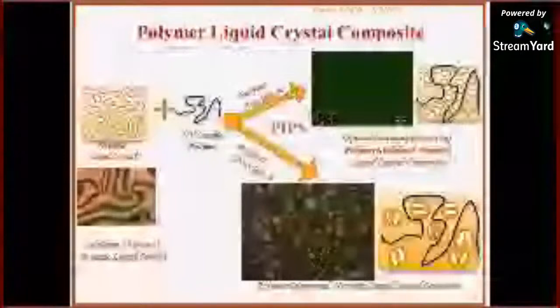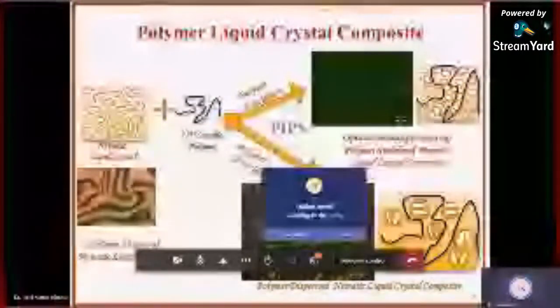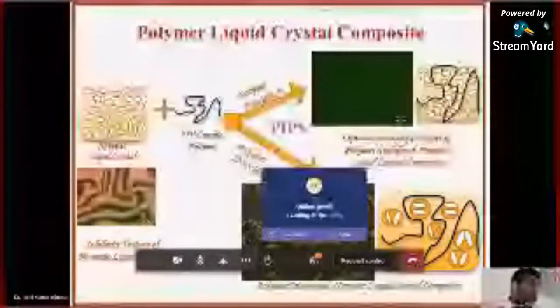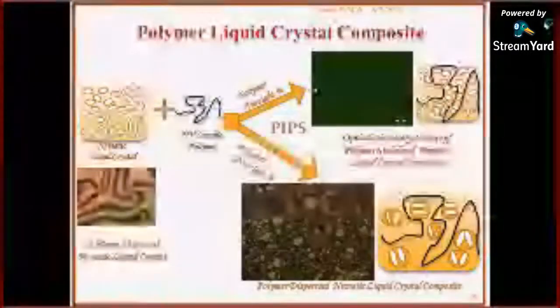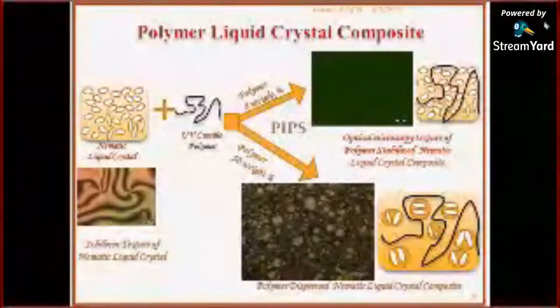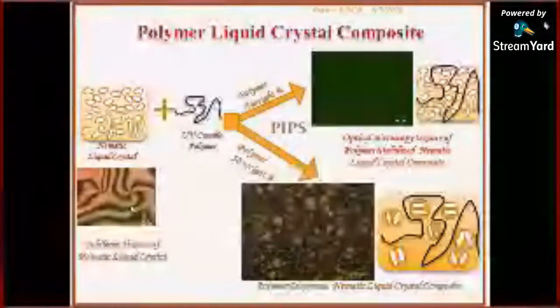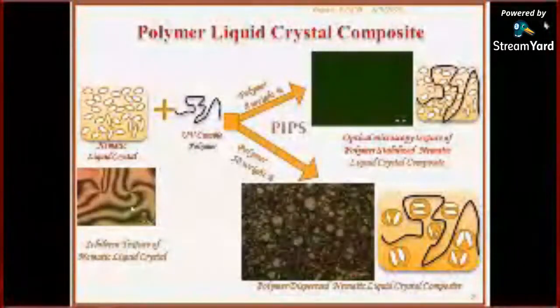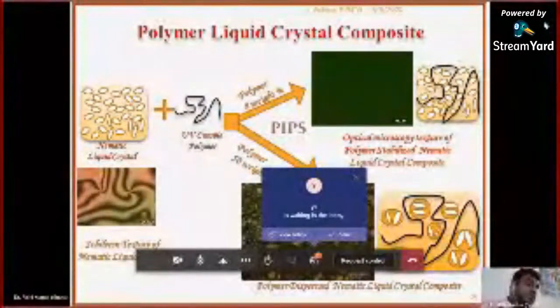So next, these are the responses of this type of material. From the start, we have this nematic material which has a thread-like structure, and we doped it with the polymer. In that case we take 8 weight% of polymer. If we take 8 weight% of polymer and 92% of this liquid crystal, we get this type of texture that is green in nature. This is called polymer stabilized texture. After UV curing, after polymerization induced phase separation, this can be achieved, and this type of texture is used to create different types of display material.